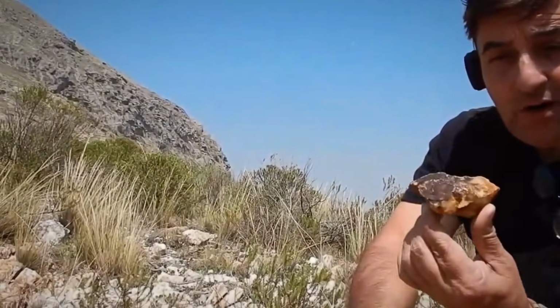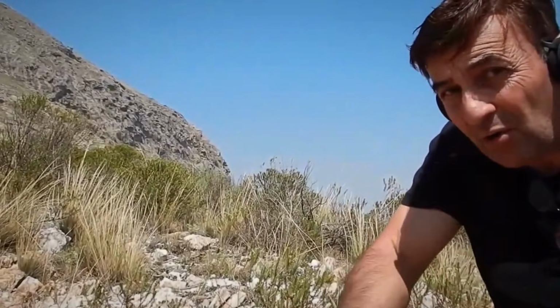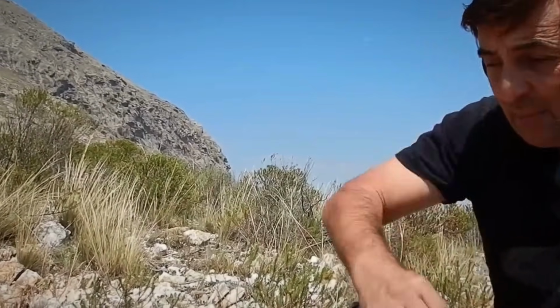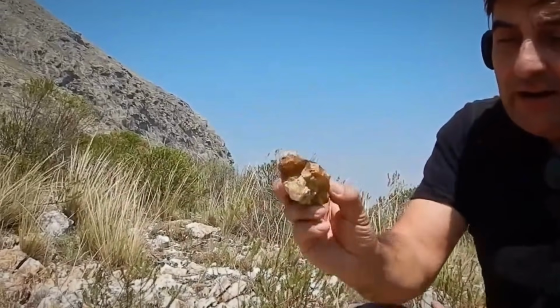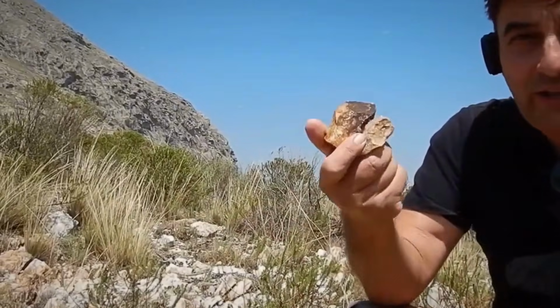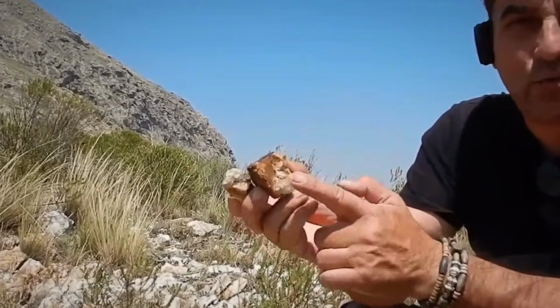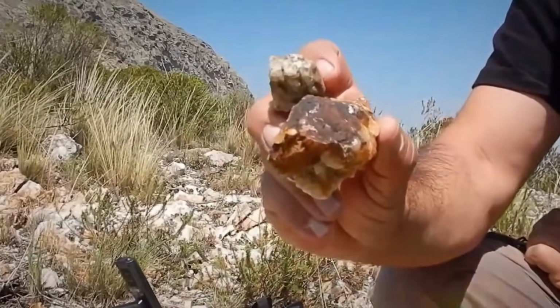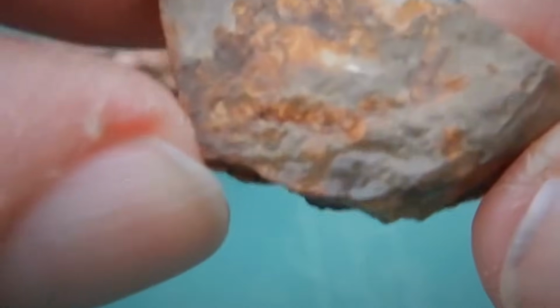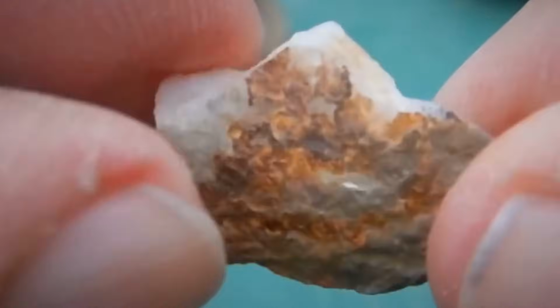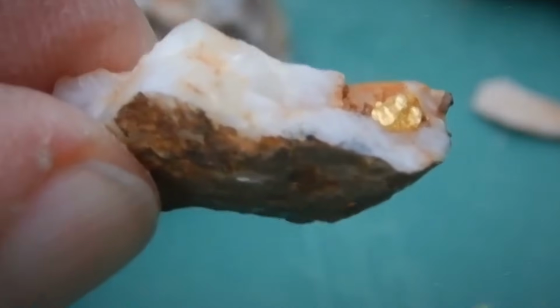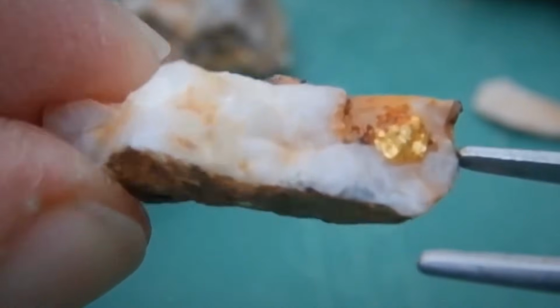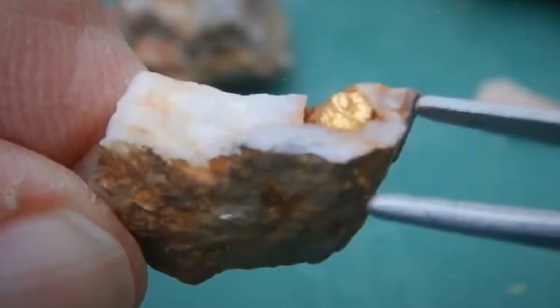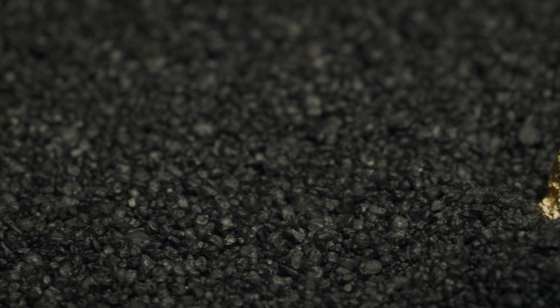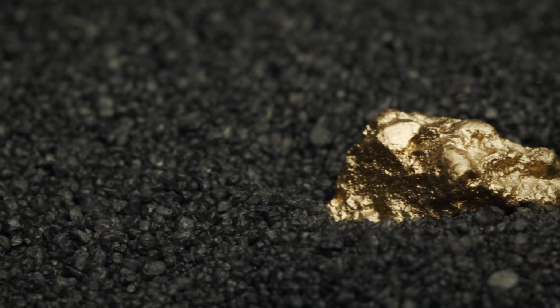Samples were prepped for a lab-based fire assay and an ICP-MS scan, inductively coupled plasma mass spectrometry, designed to detect gold in parts per million, even when hidden inside complex sulfide matrices. While costly, this test is standard in professional exploration and provides a true measure of ore grade. In parallel, a bottle roll cyanidation test was done in the field, under controlled conditions. A crushed sulfide sample was mixed with dilute cyanide solution and agitated for 24 hours. The resulting solution was tested with gold-detecting strips. A faint but positive result suggested leachable gold was indeed present, another mark in favor of chemical association rather than just free milling. This introduced a deeper complexity.